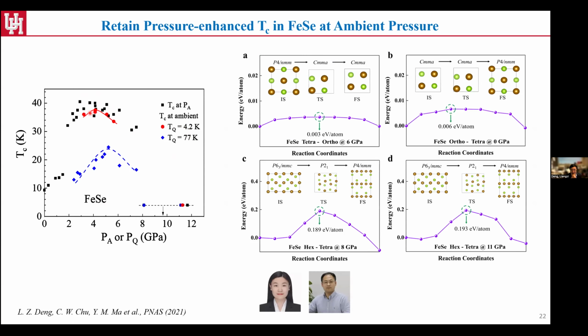So one key parameter is the energy barrier. Yanming Ma's group was kind enough to spend a lot of effort on figuring out the energy barrier between different crystal structures. Between the tetragonal and the orthorhombic phase, the energy barrier is around 3 meV and 6 meV. And the hexagonal and the tetragonal phase, which is much larger, is 0.189 eV per atom, and it's comparable to the 0.21 eV per atom for graphite and diamond. So from a theoretical point of view, it does make sense for us to quench in this phase, even though there are still many details to map out.